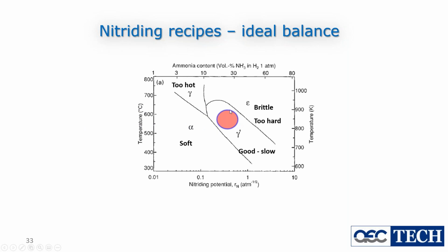So we better work in this range to make sure that the steel is not softening or tempering. At the same time, we have to control the volumetric percent or concentration of the ammonia in our gas mixture to make sure that we get gamma prime, not anything else. If it's too concentrated, we're going to go towards the brittle. If it's less concentrated, we're going to get soft nitride. So we have to make sure.